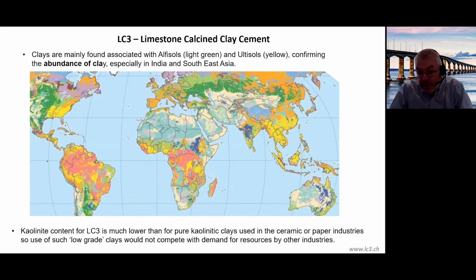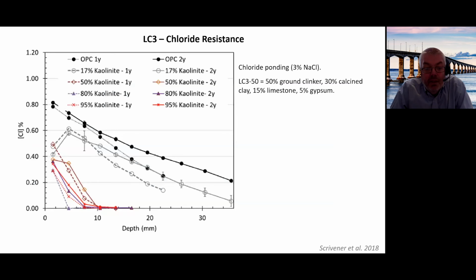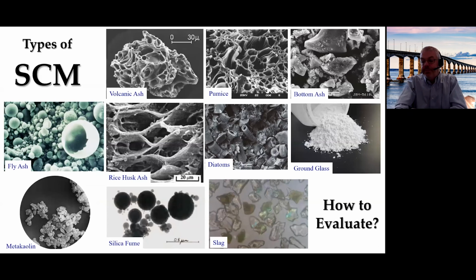Fortunately, India and China also have large deposits of clay that are suitable as well. And these are obviously countries that, should fly ash disappear from these countries, would leave a huge gap. Just demonstrating the very substantial impact these materials can have on things, I'm showing here just chloride ingress. Very much higher, many magnitudes higher resistance to chloride ion penetration.